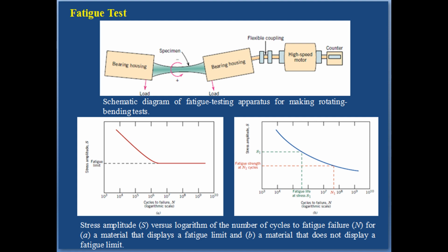Most non-ferrous alloys, for example aluminum, copper, and magnesium, do not have a fatigue limit, in that the S-N curve continues its downward trend at increasingly greater N values. Thus, fatigue will ultimately occur regardless of the magnitude of stress. For these materials, the fatigue response is specified as fatigue strength, which is defined as the stress level at which failure will occur for some specified number of cycles. The determination of fatigue strength is also demonstrated in the figure. Another important parameter that characterizes a material's fatigue behavior is fatigue life, Nf. It is the number of cycles to cause failure at a specified stress level, as taken from the S-N plot.